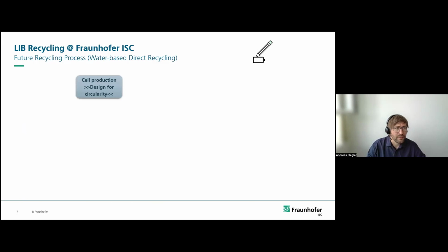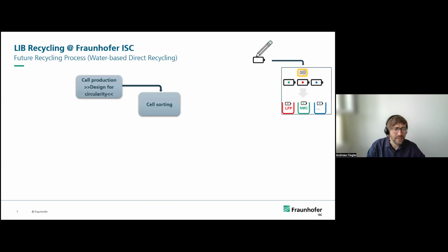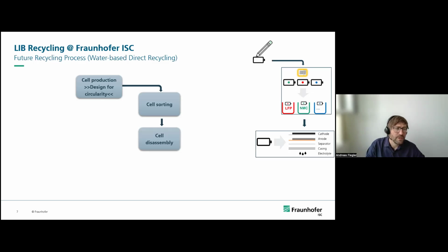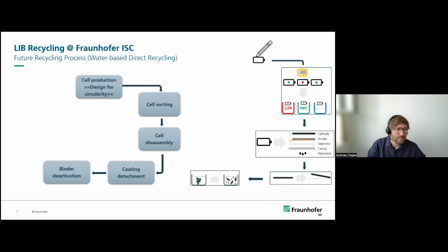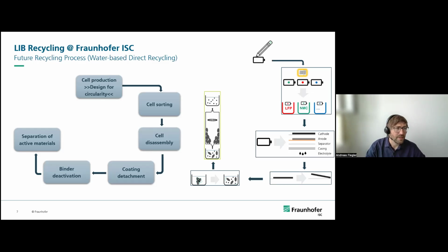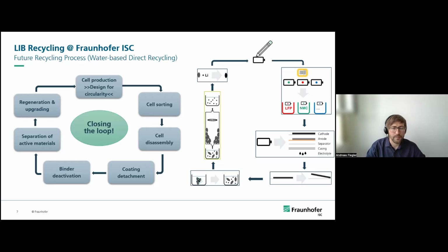So we look at different topics around the circle. We start with the design for circularity in the cell production. Then the cell sorting. Here we are focusing on the integration of marker particles as an identifier with a battery passport. Then we look at the disassembly of state-of-the-art cells and also future cells. Then we separate cathodes, anodes, separator, and the casing. And then we go to the coating detachment for anodes and cathodes. The binder deactivation, which is a very key topic in this recycling process. Then the separation of the active materials, so separating the active materials from the carbon black. Then the regeneration and upgrading, and then we close the loop and use the materials again. In this talk, I will focus on these process steps, and I start with the design for circularity in the cell production.